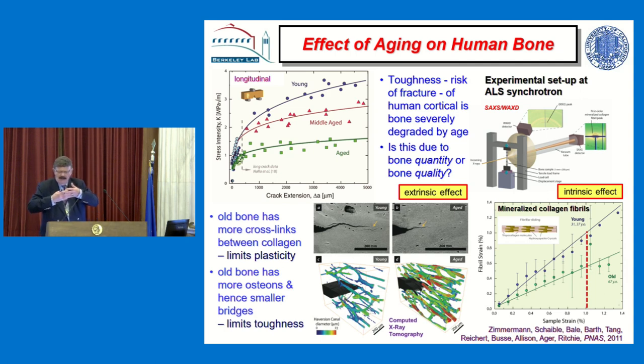Remember, the collagen is what causes the deformation. So if we look at this plot here, this is the strain in the bone, what we've just measured. And this axis is the strain just in the collagen. So if I look at, say, a strain of about 1% in young bone, which is the upper line here, of that 1% strain in the bone, virtually all of it is carried by the collagen, which is what you'd expect because the mineral is too stiff. But if you look at old bone, instead of having most of the strain carried by the collagen, it's much lower now. The strain in the collagen is only about 60% of the strain in the bone.